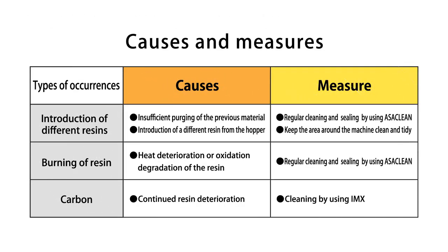The use of ASACLEAN can reduce deposits and contaminants generated from inside the molding machine. The first step is the measure for the introduction of different resins. The cause is assumed to be insufficient purging of the previous material or the introduction of a different resin from the hopper. The measures that can be used to prevent these types of occurrences are regular cleaning, sealing using ASACLEAN, and keeping the area around the molding machine clean and tidy.